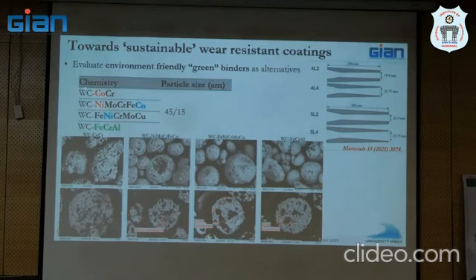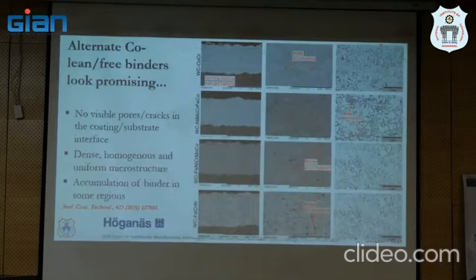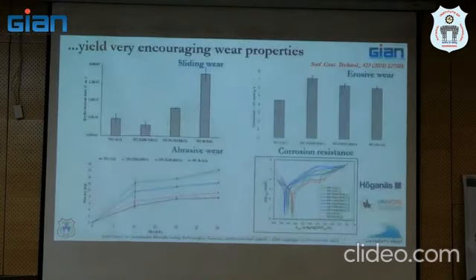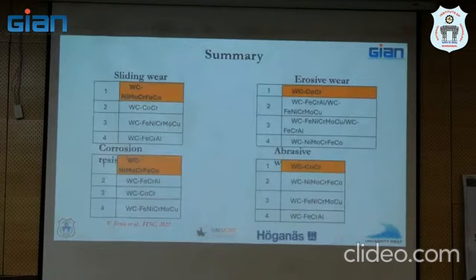We work on this with Höganäs, and they have made for us all these different kinds of formulations. The nice thing is, with all of these alternative binders, we get outstanding coatings, right? Same percentage of binder, but the binder chemistry is different. Some of it is completely cobalt free, right? These two, for example, we get excellent coatings. So that was step one, right? We have investigated it almost to death. This is a little complicated slide, but if you look at the summary, depending upon what kind of surface degradation you are talking about, some of these are even better than the tungsten carbide cobalt chrome, which is the reference material. In some cases, they are almost as good.